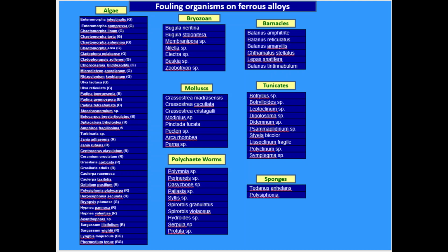So these algae, soft fouling organisms, enhance the oxygen corrosion rate of metal submerged in seawater when they attach on it. At the interface, the algae, by photosynthetic activity and also by putrefactive action when they decay, enhance the corrosion of the materials on which they attach.